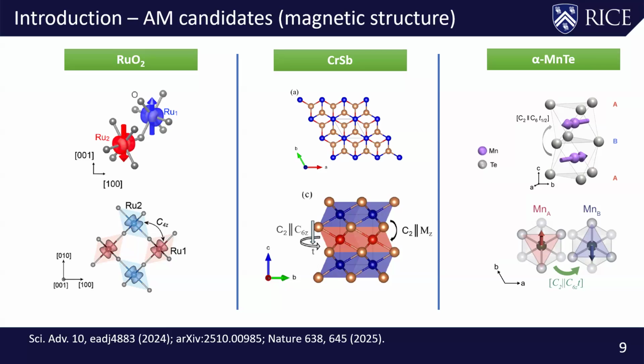But the most interesting one, in my opinion, is the so-called hexagonal manganese tellurium. The reason this system is very interesting is that even though it has the same magnetic structure as chromium antimony, the actual moment is in the plane. It has been shown through a magnetic space group argument that with this magnetic symmetry you could, in principle, have anomalous Hall effect, and yet the system has very little magnetization and very little ferromagnetic component.